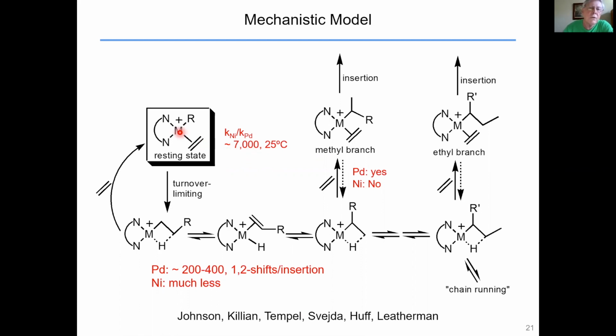Once this undergoes migratory insertion, indeed you generate the agostic species, the beta agostic species. And the reason you get branching is that this can beta eliminate and reinsert, and the metal walks 1 carbon down the chain. So this is a primary attachment. It marches 1 carbon down to generate this species, a secondary species with an alpha methyl group. If this binds ethylene and inserts, you put a methyl branch in the chain. If this walks another carbon down the chain, now you have a C2 branch. If this binds ethylene and inserts, you put an ethyl branch in the chain.